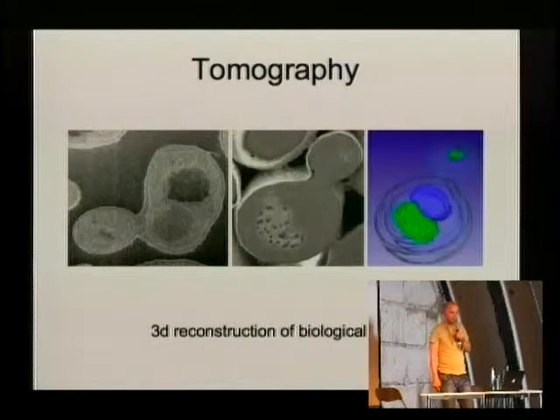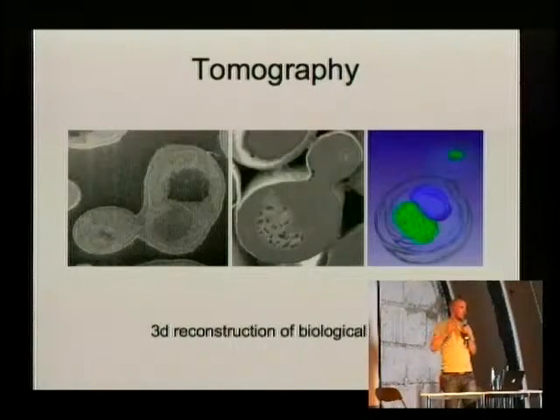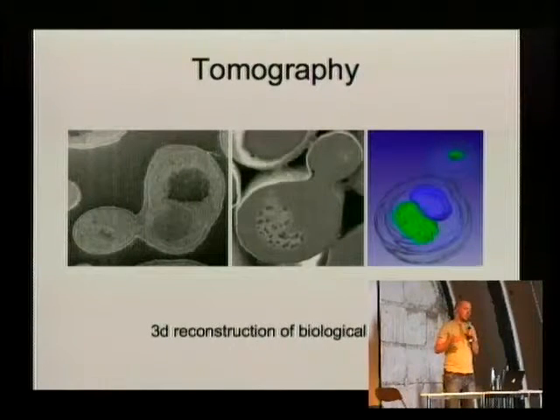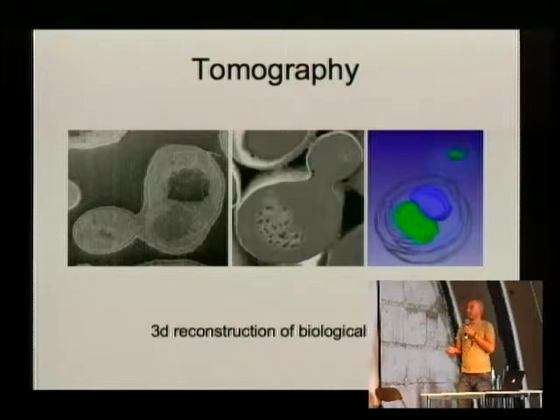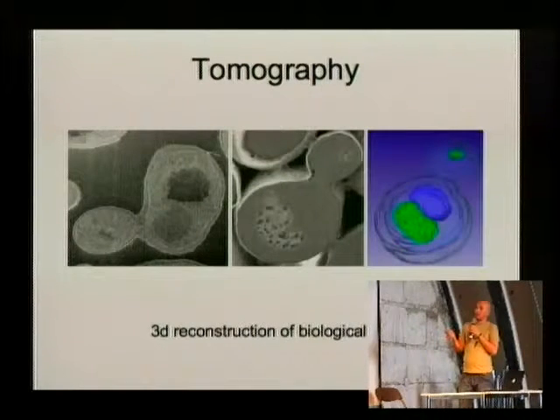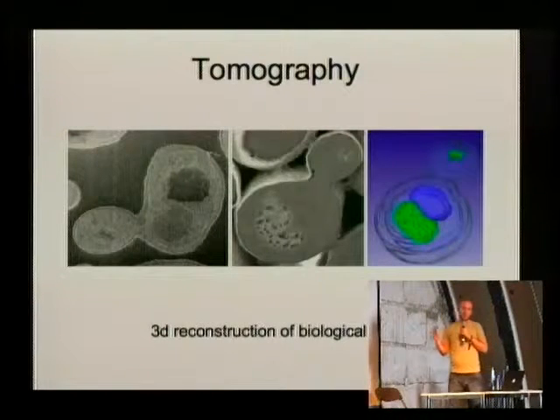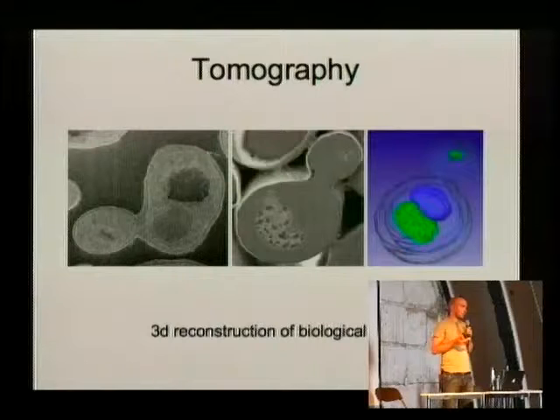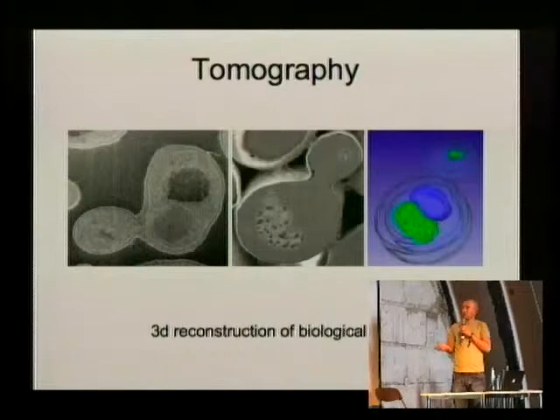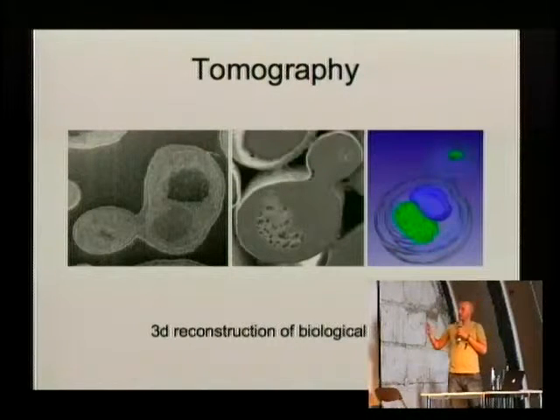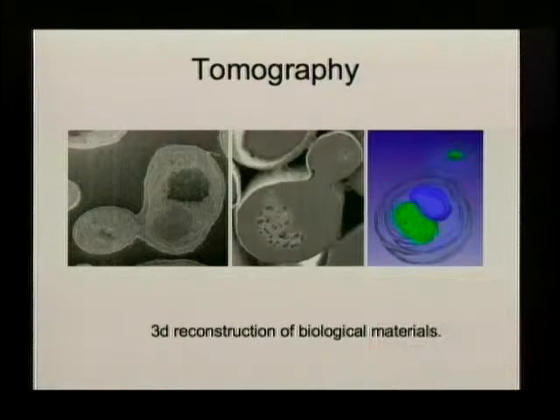Another nice thing is, since you are able to make very thin slices, you can make the slices and after each slice take a picture and then run this series of pictures through the computer and get some tomography or some 3D reconstruction. So in this case that was done on a biological sample. For this, it used to be that the samples had to be prepared in a special way, frozen or embedded into some plastic. But actually nowadays even that is not necessary anymore. You can have a certain pressure in the microscope, so you can, not exactly living cells, but almost living cells, cut them apart and look how it looks on the inside.